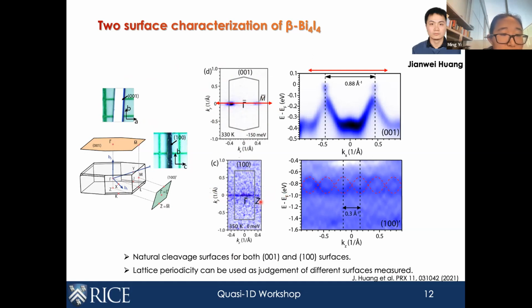So they're distinct. And not only that, we can also look in the energy dimension by taking a cut, and you can look at the periodicity of the bands. And from the periodicity, we can match that to the inverse of the lattice constant along different directions and confirm that indeed this one is coming from the 001 surface. And this quasi-1D Fermi surface is associated with the 100 side surface.